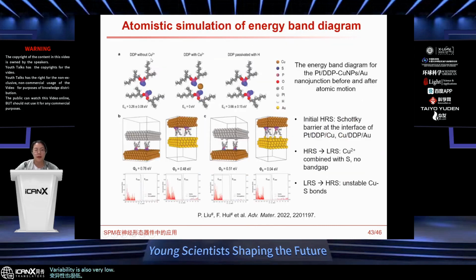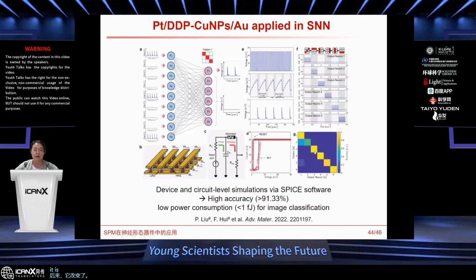So this is record low switching voltage, and we can see it is highly reproducible, and the variability is also very low. And by using the atomistic simulation, we also analyzed the physical and chemical mechanism. The initial high resistive state is caused by the Schottky barrier at its interface, and afterwards it switches back and forth between low and high resistance because of these unstable copper and sulfur bonds.